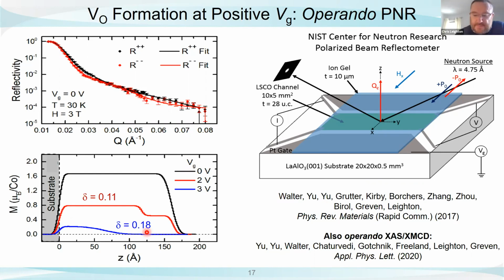So what we're doing here is we're basically taking a material that's got a ferromagnetic Curie temperature of about 230 Kelvin. By applying a voltage, we can dial up any TC we want down to essentially 20 or 30 K. Now, key question, if we then go to negative voltages, can we revive the ferromagnetism and make a uniform cycle? And I'll show you in a few minutes here that we can, okay? First, I just want to answer the question, how is it that we can apply a surface electric field up here and get this redox activity at the bottom of the film?